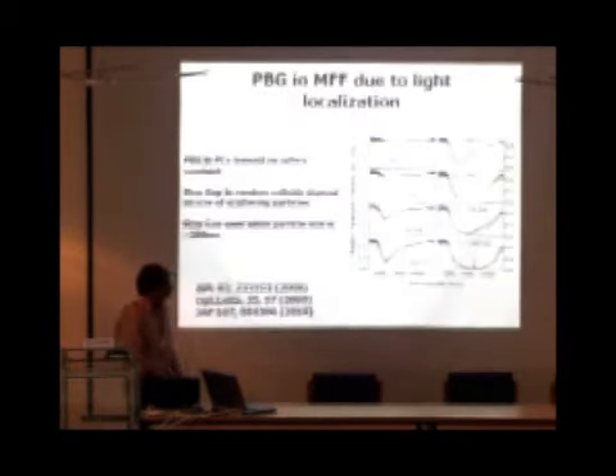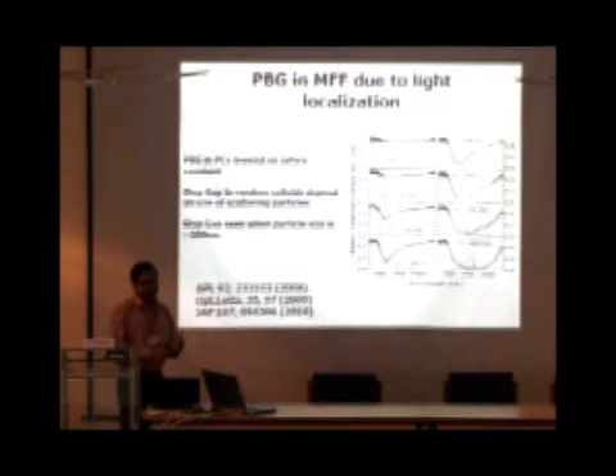So what happens is we first find the optimum intensity required for the optical trap light, and then vary the magnetic field. As we vary the magnetic field, the cluster size increases. What we calculated is that we require about 200 nanometers as the optimum size of the cluster for this case, which is 1.55 micron wavelength.